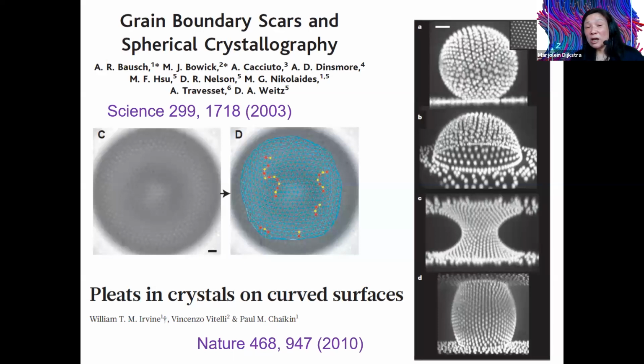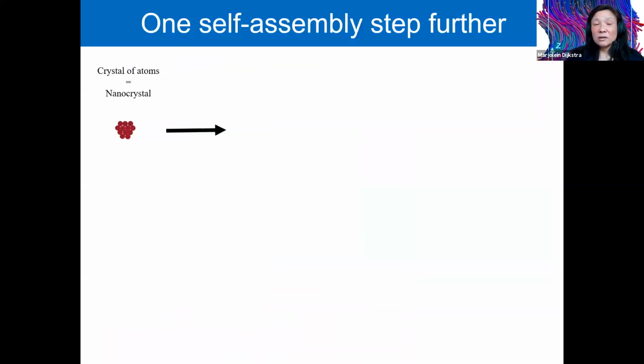And one can also adhere particles at the interface. These are, for instance, systems of oil and water, and the particles like to be at the interface, or they adsorb to the interface. And one can see that one can obtain whole lines of disclinations, which are also called scars or pleats in crystals on curved surfaces.